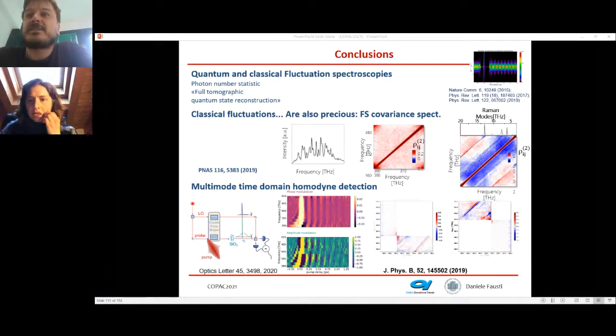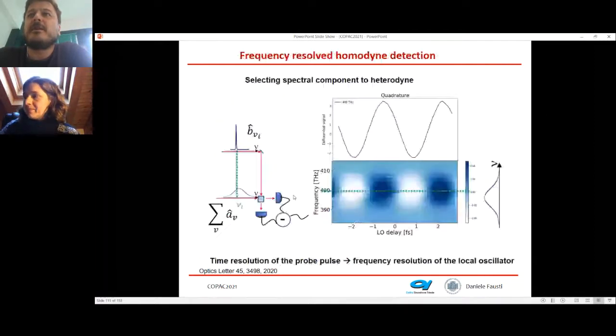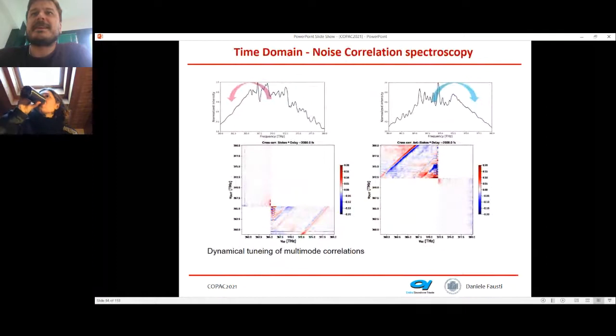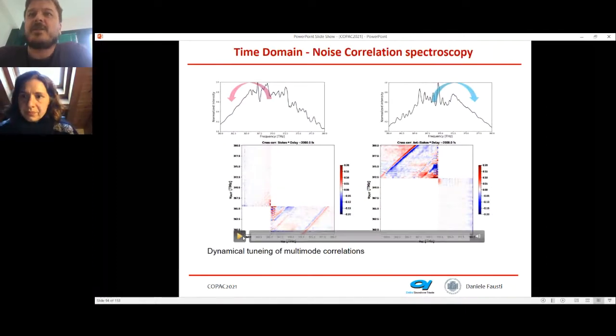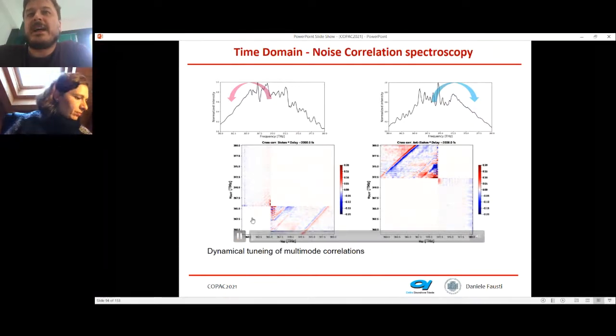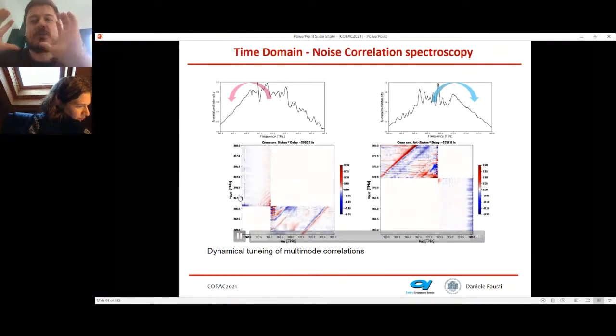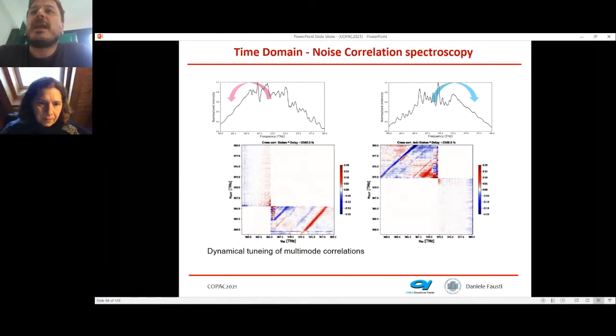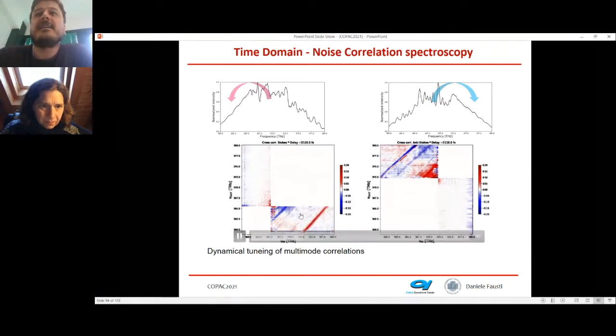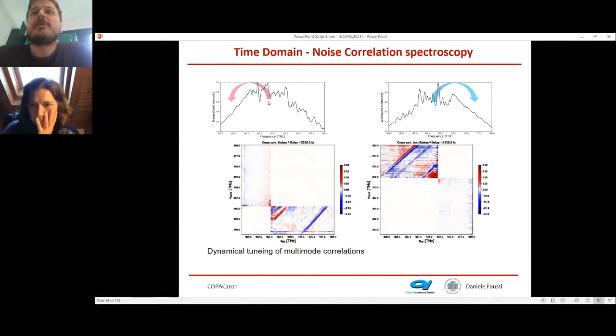Yeah, exactly. So this is what I actually showed. Let me just go back to the slide. So it's unpublished. But basically here it's this fluctuation correlation spectroscopy as a function of time. So this is an experiment where we did some photoexcitation with a short pulse and some correlation measurement, as I showed you in the talk, just by measuring the single shot correlations. And all those lines that you see here, this corresponds to the phonon modes. And you can shape your pulse so that you select only scattering process, which are from high energy to low energy, as you see on the left, and from low energy to high energy, as you see on the right.